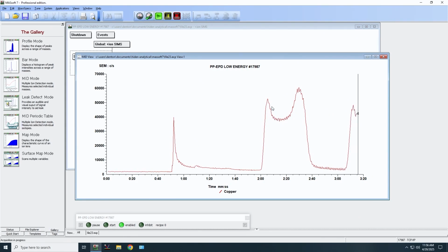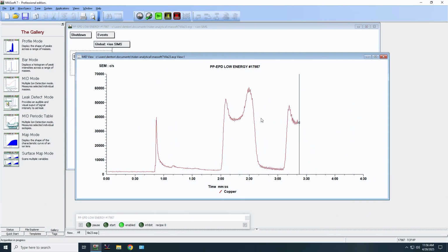What happens is that, because of the way we deposited the sample, there's a little bit of oxygen at the interface between each material. Copper is here and silicon is here, and in between each layer there's a little bit of oxygen that got absorbed while it was waiting for the transition to the next material layer. So this peak here is because of that oxygen basically enhancing the copper signal.